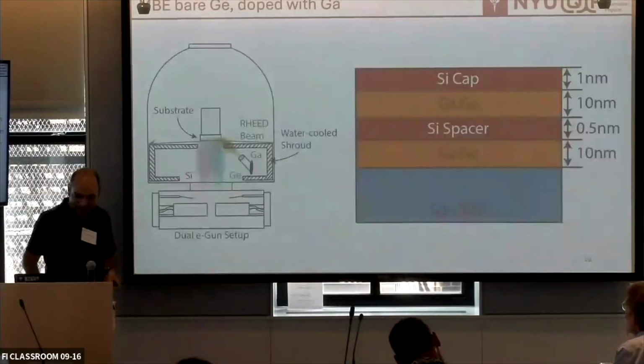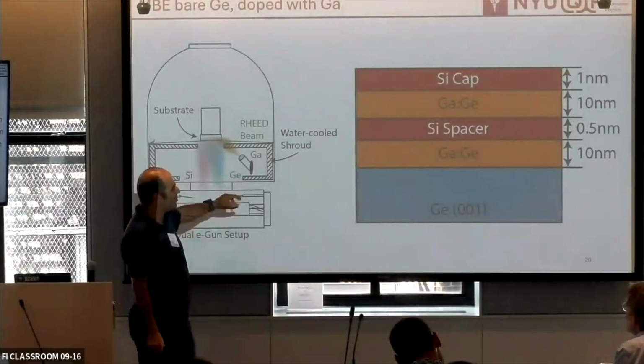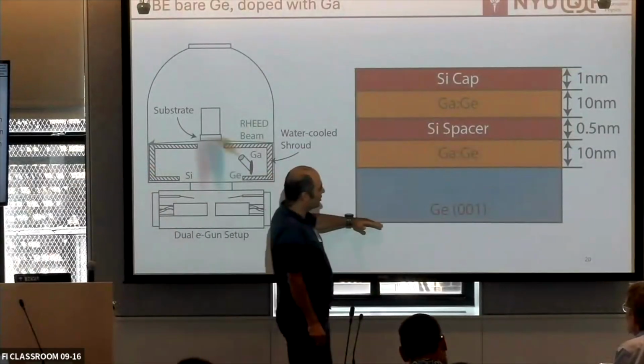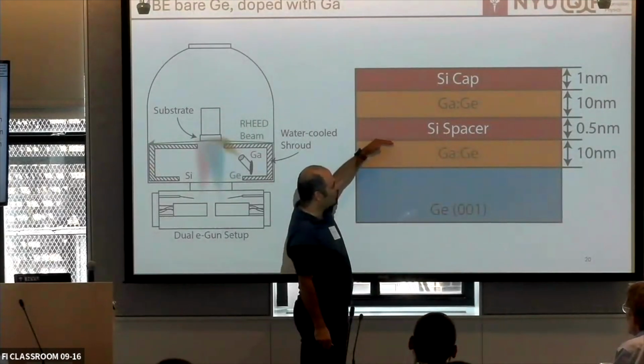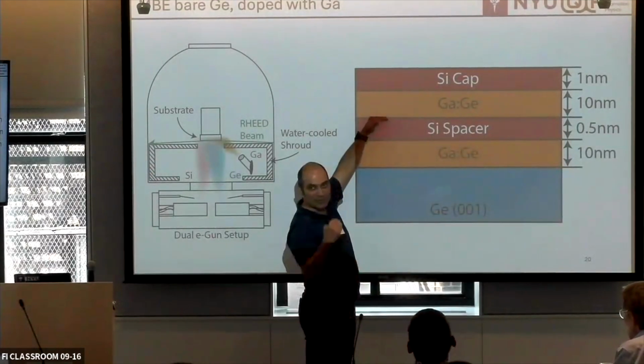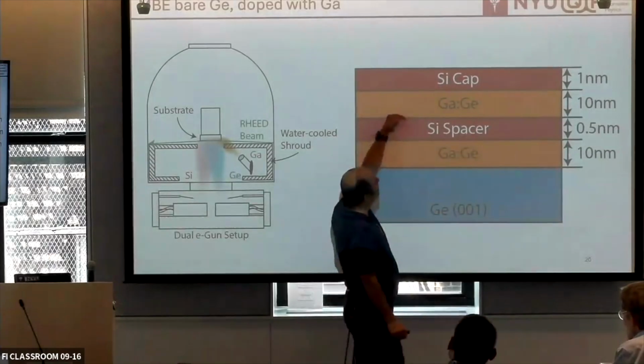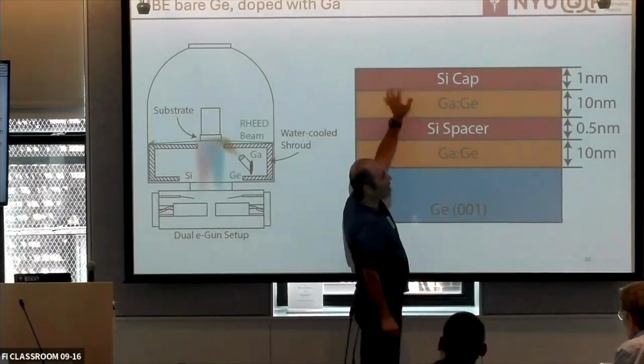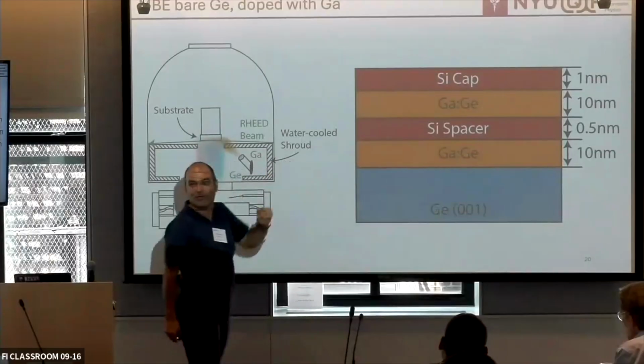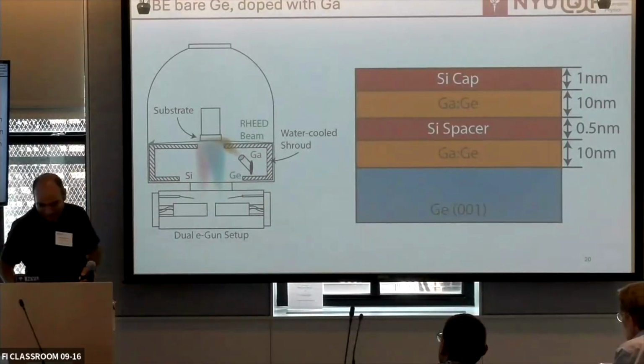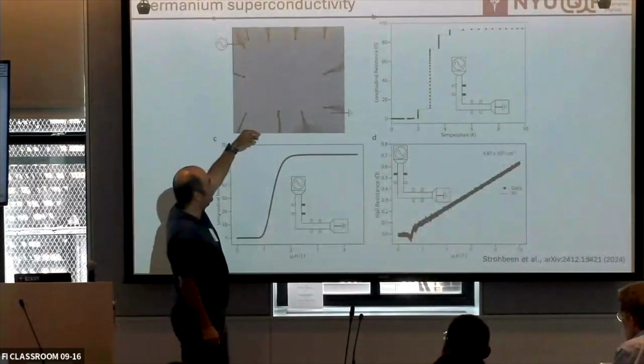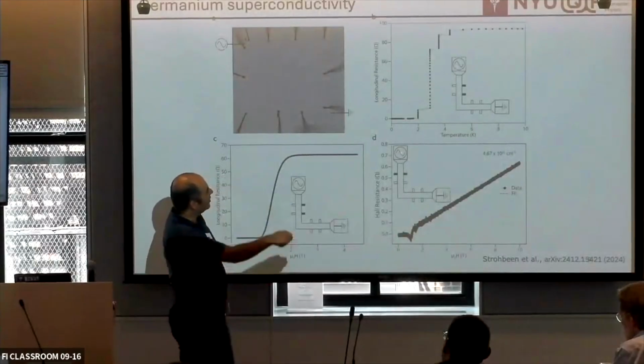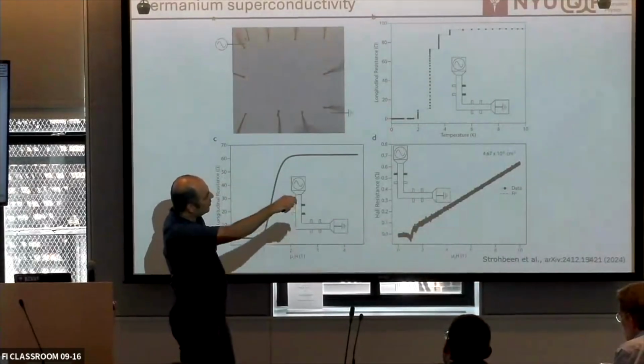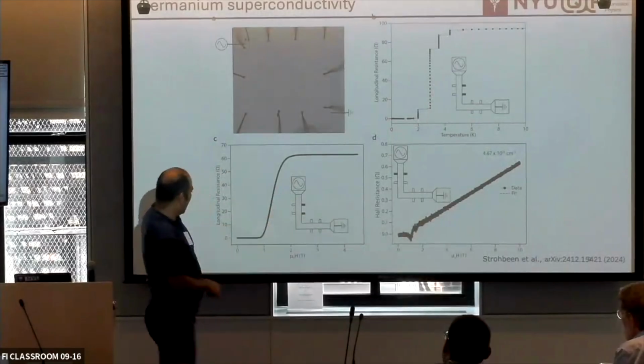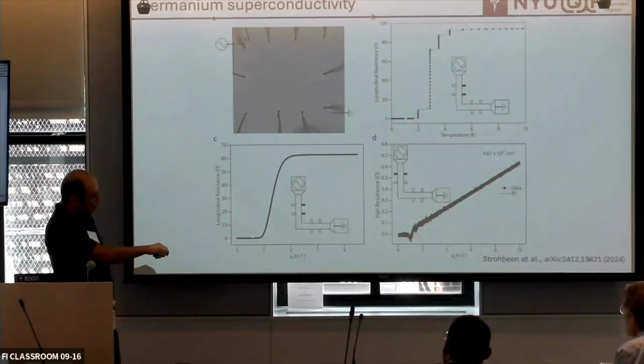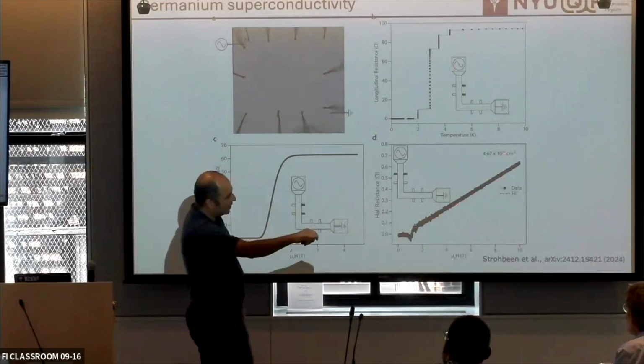So with the MBE, and I'm not gonna bore you with the exact material science that went behind it, we decided to grow this. So basically this is the germanium substrate, we dope it. In silicon, the spacer is just trying to kind of interrupt the superconductivity. We create another layer that we think is a superconductor and we end it. So it's like a Josephson junction vertical, right? So we tried this. You kind of make a whole bar again out of this, and then you measure it. And this is R versus temperature, and then you see that something superconducts. This is the critical field measurement. This is the Hall. We can get densities out.